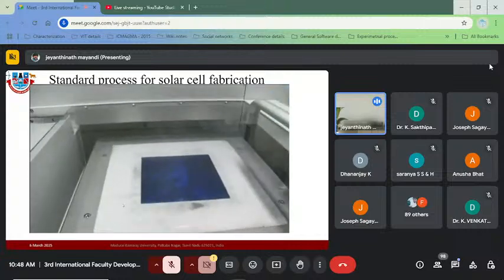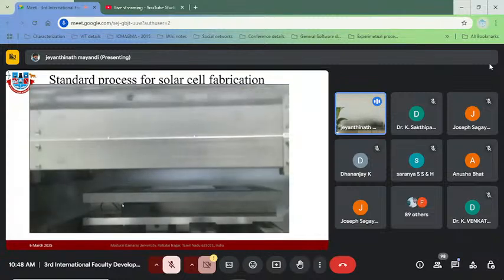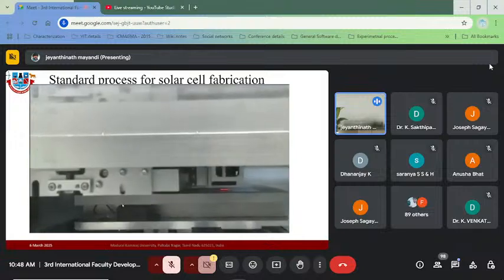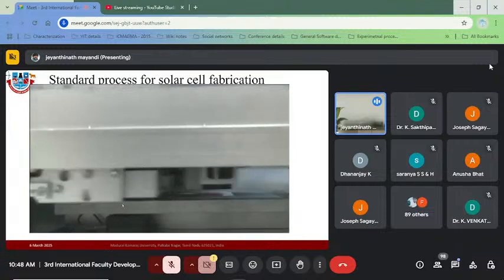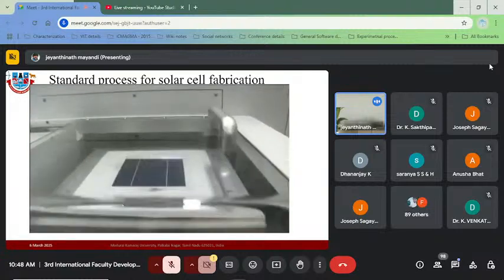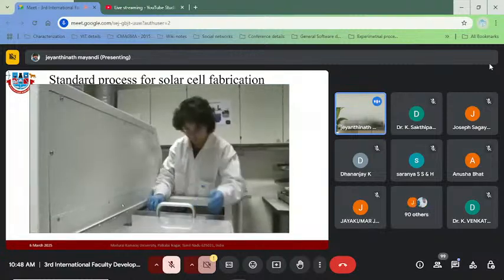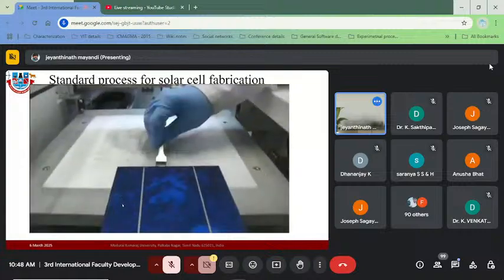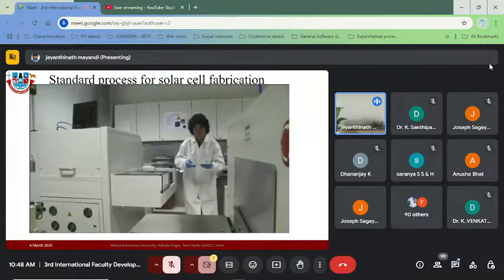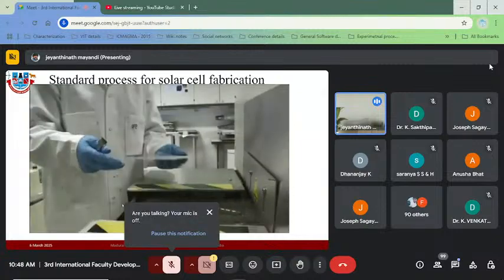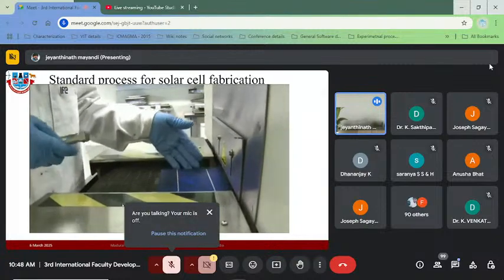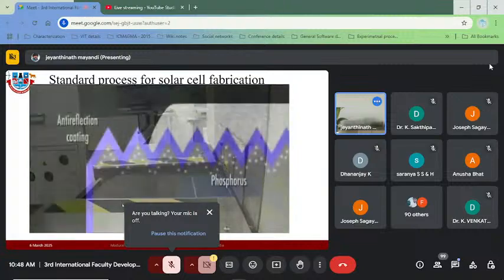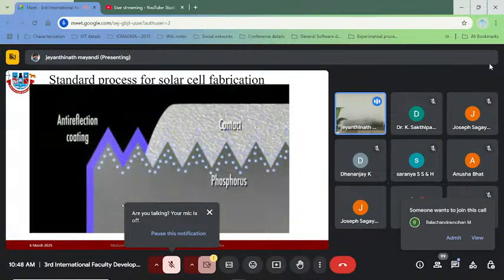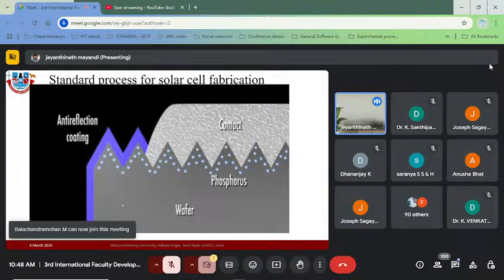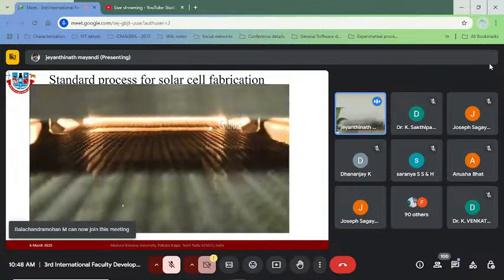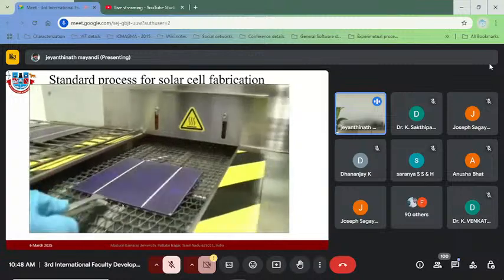On the front side, the contacts need to be as close to each other as possible to minimize electrical resistance, but at the same time far enough apart to let as much light in as possible. The solution is a grid type of contact. On the back side, it is common to cover the whole area with metal. To get the contacts through the anti-reflection coating, we need to fire the contacts. We need to heat the contacts up. To optimize the process, we can change the temperature profile, or we can change the metals that we use.